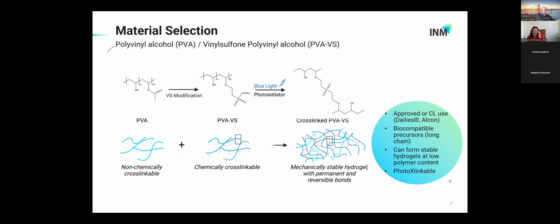Now, if you think about material selection for such an application, let's focus on the requirements that we need for a living contact lens, for embedding a material. What we need is, ideally, a material which is already approved for contact lenses. So we started with polyvinyl alcohol. There are commercially available contact lenses based on cross-linkable polyvinyl alcohol modified with acrylate groups. Ideally, if you want to make it compatible with the cells, you do not start from toxic precursors. That's good for PVA because to make cross-linkable PVA, we typically start with long chains, which are also typically less toxic than short chains for mixing with the cells.